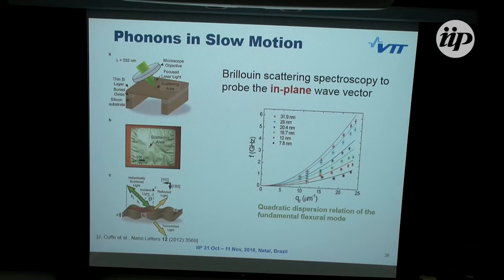So the results from these measurements, so-called phonons in slow motion. When one tilts the probing beam, one can probe the in-plane wave vector properties. And here is the measurement of the first flexural mode, and this is the wave vector, or the cut from the angle here, and this is the frequency of the peaks measured, and you can see that it's a quadratic dispersion relation, and these are measured from several different thicknesses of membranes. And it's quadratic, so then we get the phase velocity, which is linear, and then also the group velocity is linear on the wave number or wave vector.